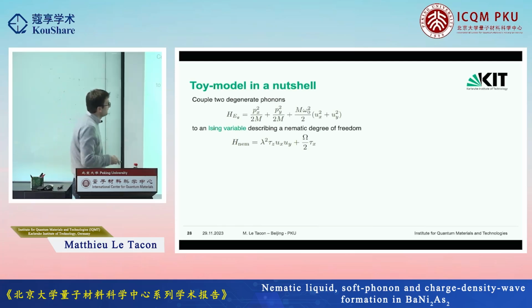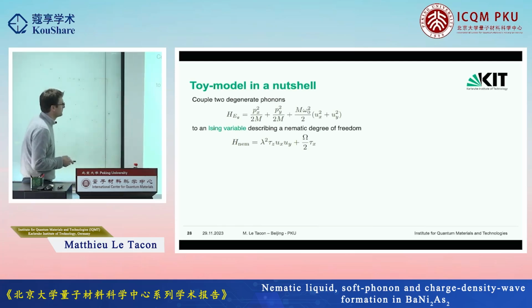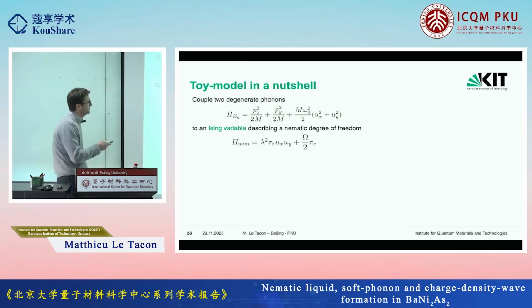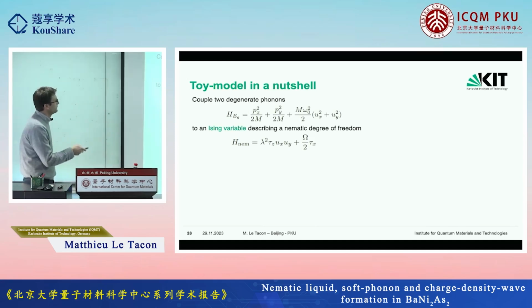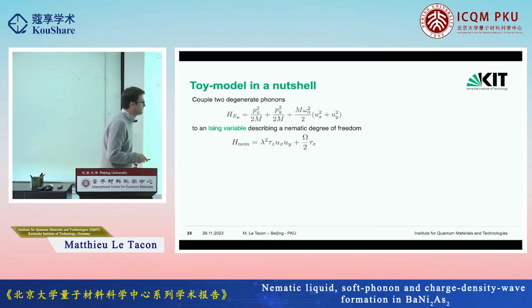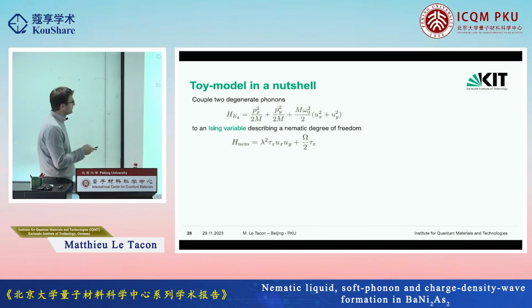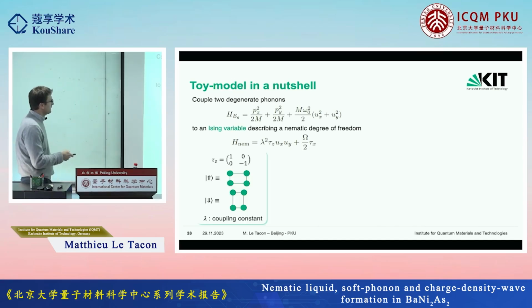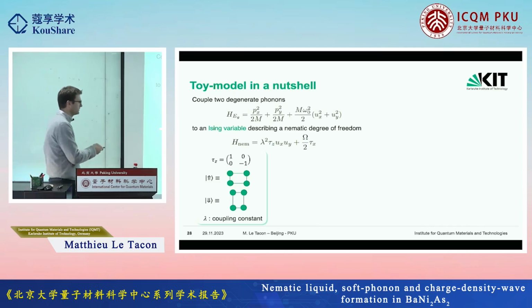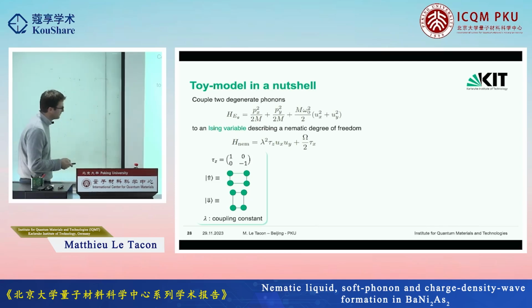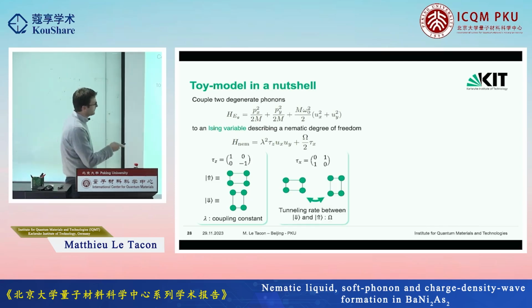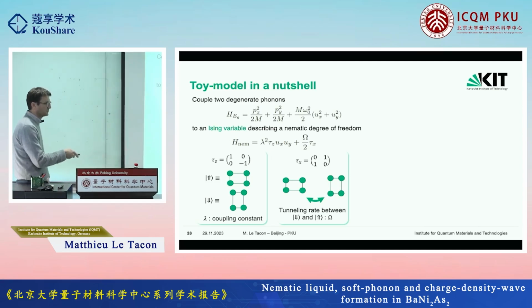And in a nutshell, he made a very simple toy model to try to account for that. And the idea is that you take two degenerate phonons. So here is the harmonic oscillator for your two degenerate phonons. They have the same frequency omega 0. And you couple them to an Ising variable that describe a nematic degrees of freedom. In short here, what you see is pretty much you have two degenerate states. So basically a distortion along A, or so A is the long axis or B is the long axis. And you can call this a spin up and this a spin down. So these are your two eigenstate of this nematic thing, and you allowed tunneling between these two states at a rate omega. Okay, so you get a tunneling rate between these two configurations.